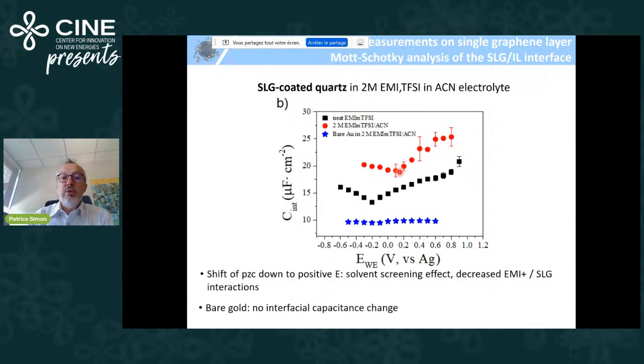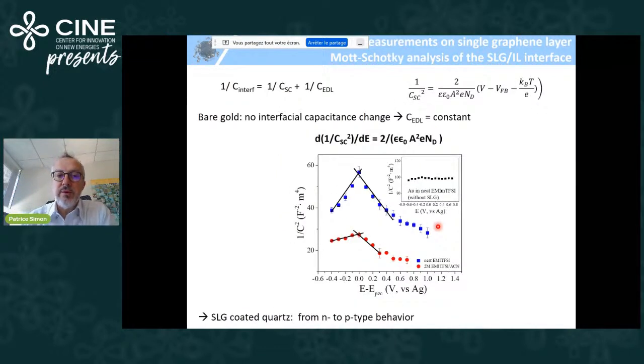Here, you decrease the ion-ion interaction because there is a solvent to screen this interaction, and then you decrease the carbon-cation interaction. You shift the pzc to a positive value. And for the bare gold, which is the double layer capacitance, there is no change of double layer capacitance if you use a bare gold electrode.